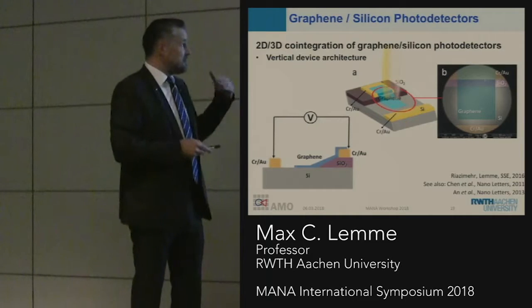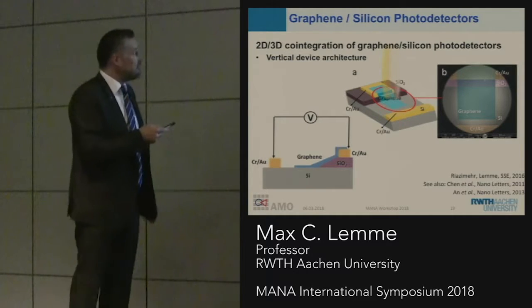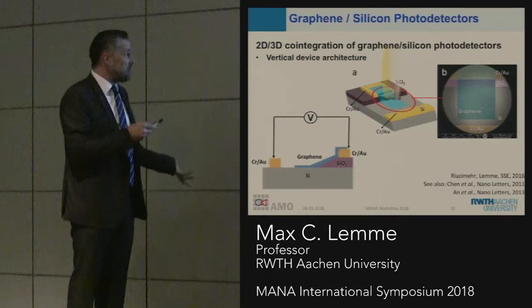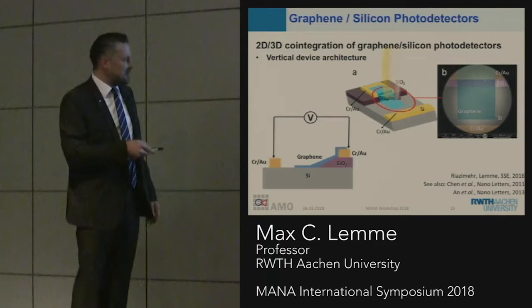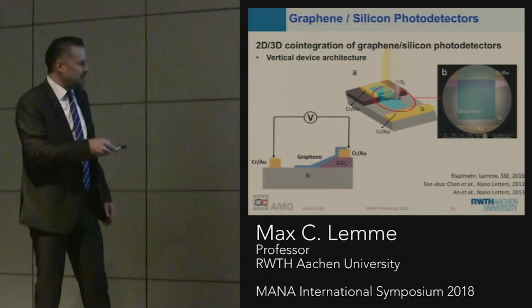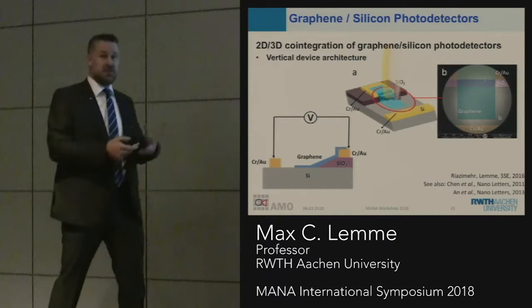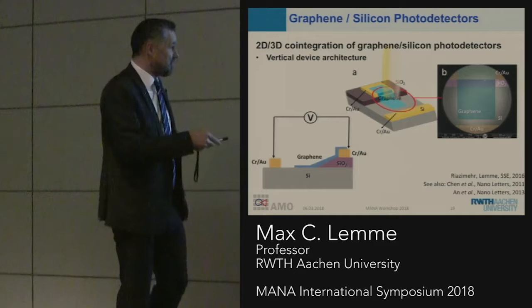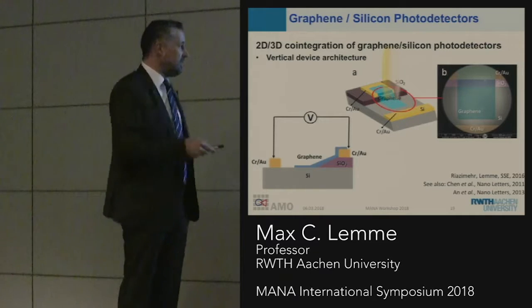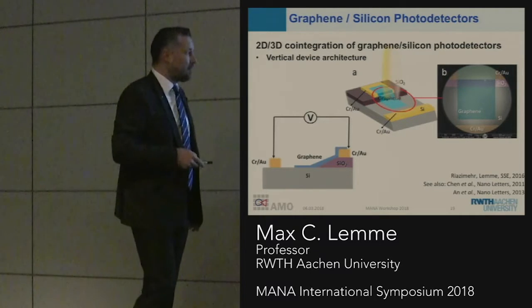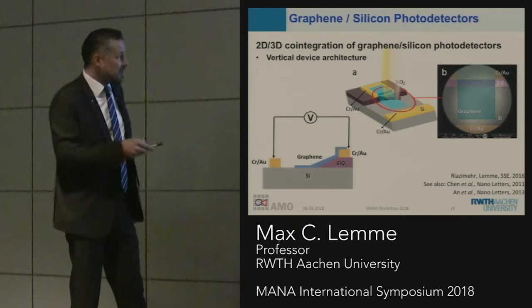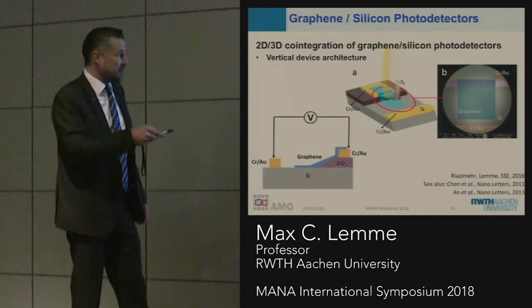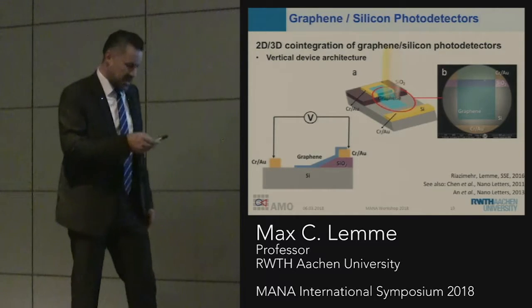We started doing this by integrating graphene with silicon. Here we have 2D, 3D co-integration. Basically, we have a silicon substrate, we put a graphene patch on top, and we contact the graphene and the silicon, so we have a Schottky diode, because graphene is semi-metallic, and if we choose the right type of silicon, we can get a Schottky barrier. This is the top view, and this becomes the active area of our diode.